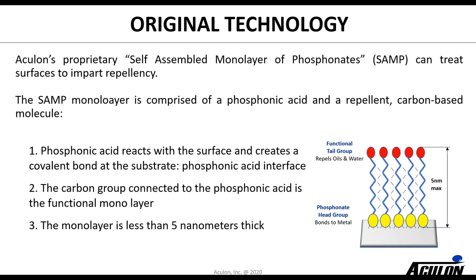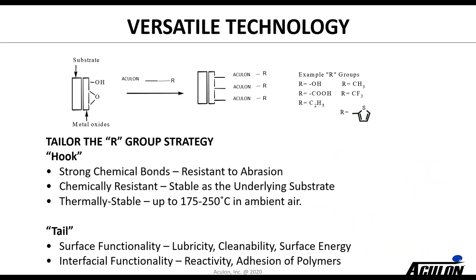When the company started back in 2004, it was based on some technology license from Princeton University relating to self-assembled monolayers of phosphonates. And that's a very good versatile technology where we're able to basically bond the SAMP into the oxide layer on that surface. It's a phosphonic acid, and basically we're able to tune the functional tail group to repel oil, water, and other types of things. And it's a monolayer, it's less than 5 nanometers thick. That technology was versatile in that we could basically tailor that R group to create strong chemical bonds, to be resistant to abrasion. It was chemically resistant, it's thermally stable, and lots of different functionalities that we could do then. So that was the start of our company.